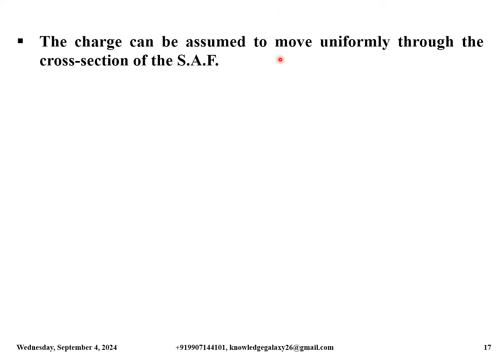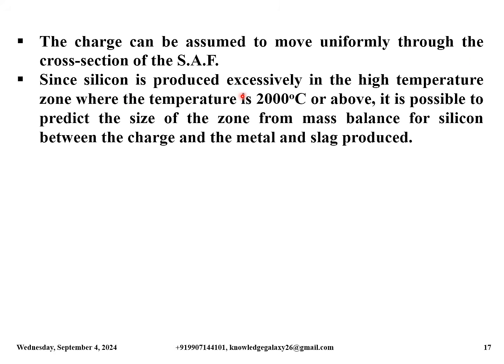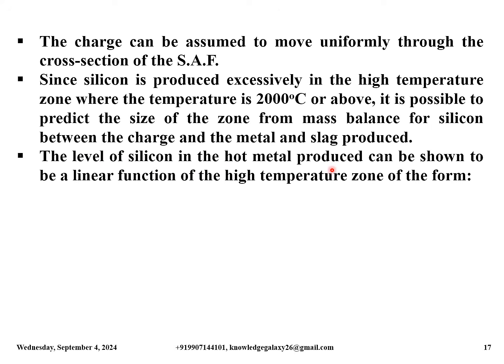Okay, now coming back. The charge can be assumed to move uniformly through the cross section of the SAF. Since silicon is produced excessively in the high temperature zone where the temperature is 2000 degrees Celsius or above, it is possible to predict the size of the zone from a mass balance for silicon between the charge and the metal and slag produced. The level of silicon in the hot metal produced can be shown to be a linear function of the high temperature zone of the form